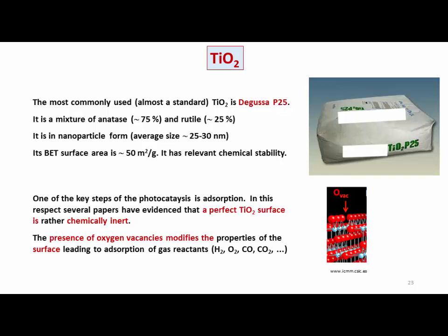The important thing that I was introducing before is this: if you have a very perfect surface, there is no effect. So what is wrong on the surface is critical. Essentially, it appears that oxygen vacancies or titanium vacancies are the key points for good photocatalytic activity. If your carriers get to the surface and the surface is perfect, there is no absorption site, and there is no way to interact with the solution. Here is where the solution can be absorbed. So essentially, you need a perfect bulk and a very different surface. Which is not the case for electronic problems, where surface defects are detrimental. In this case, you are looking for surface defects, to engineer them properly without getting defects in the bulk.